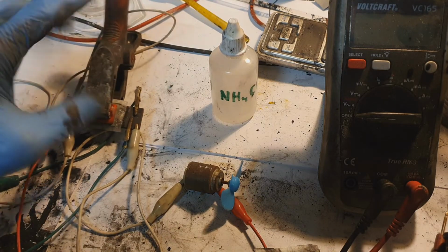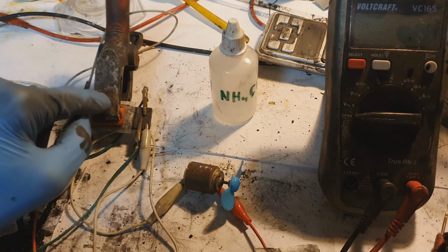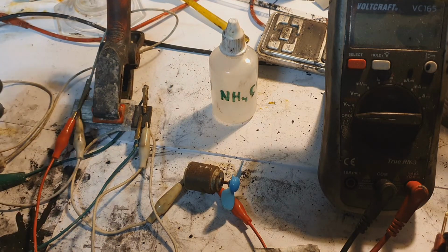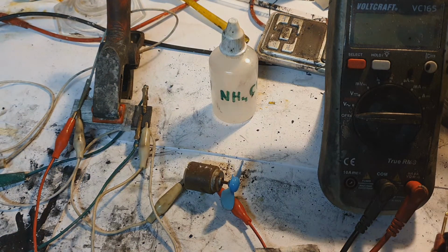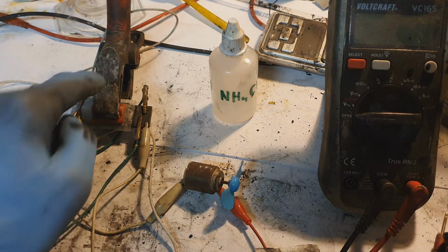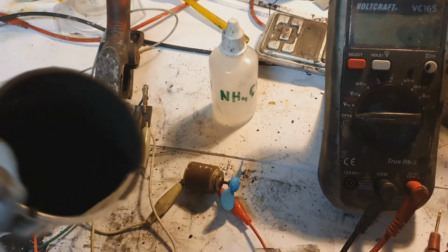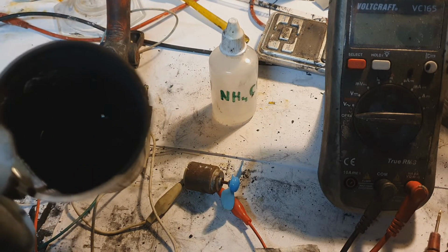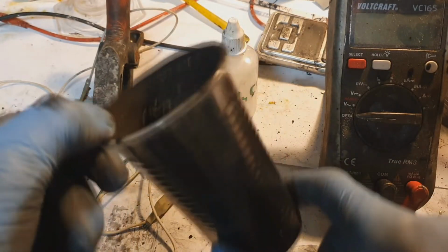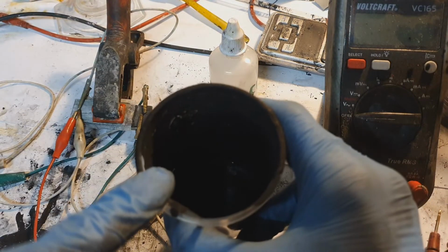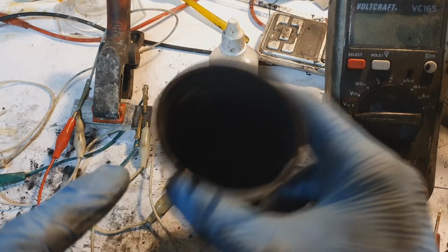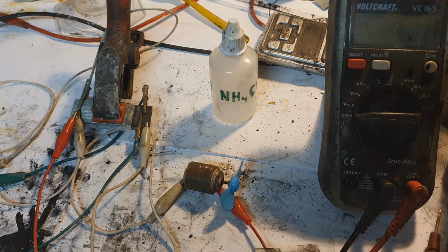Because right now in this cell I have some binder, but this binder is not some normal binder like PVA or something similar. The binder which I use in this cell is my new water-based conductive ink. So actually I will make some review about this ink also. But what I used for the binder was this conductive ink. And only with adding the conductive ink for the binder, I improved the power output from 200 milliamps to 1 amp, and also the capacity is 2 times, 3 times better than before.